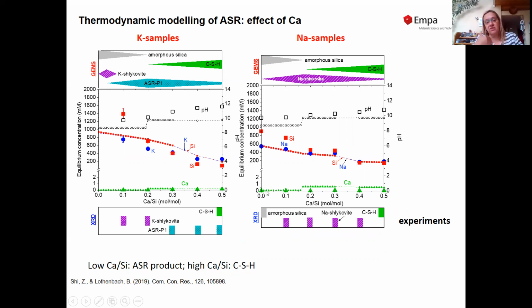If we calculate what happens in the absence of calcium, we predict amorphous silica, and we only start to predict the formation of sodium shlykovite if we have some calcium present in the samples. If we go to more calcium-rich samples, then we start to predict the formation of CSH, which actually agrees well with the experimental data. The potassium samples are a bit more complicated because we have two ASR products, the shlykovite and the ASRP1, which is the amorphous one. But again, we see the same sequence.